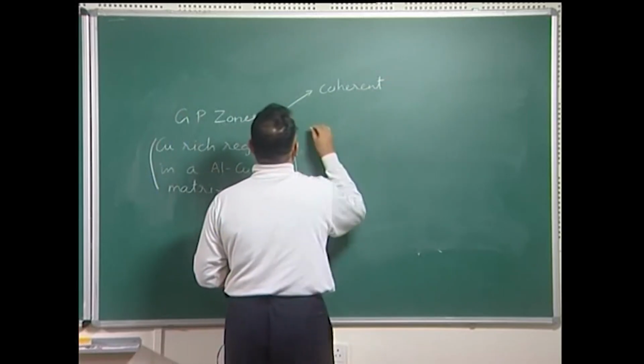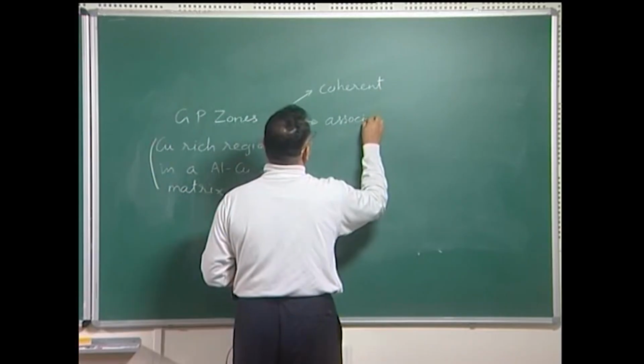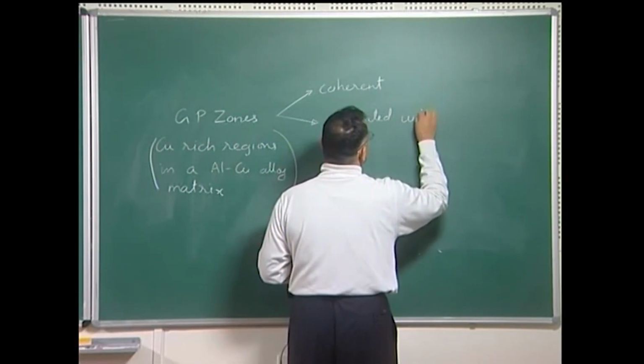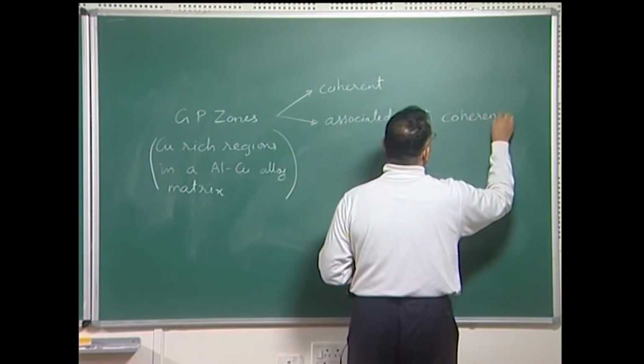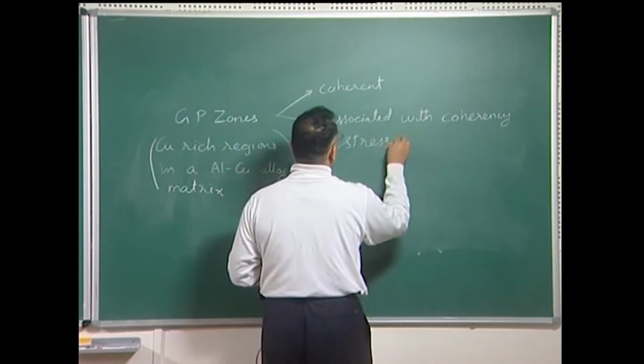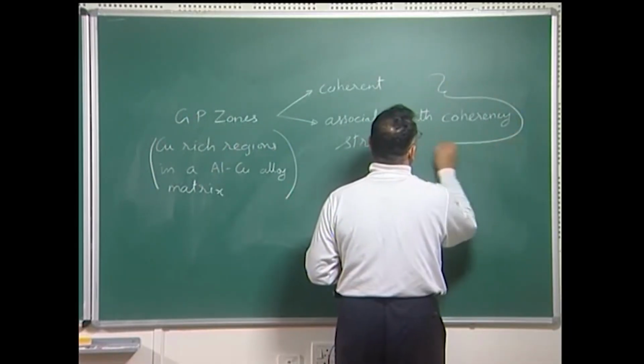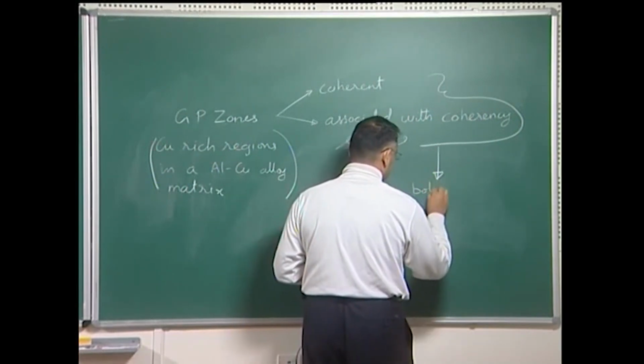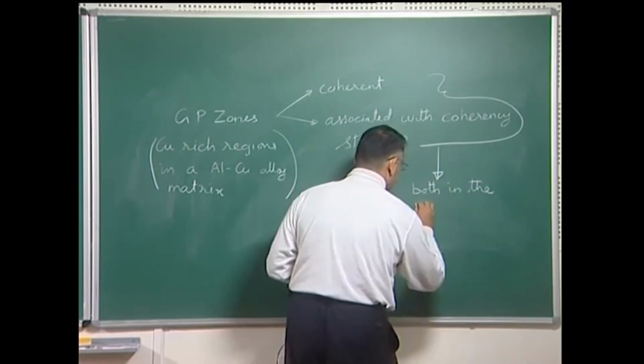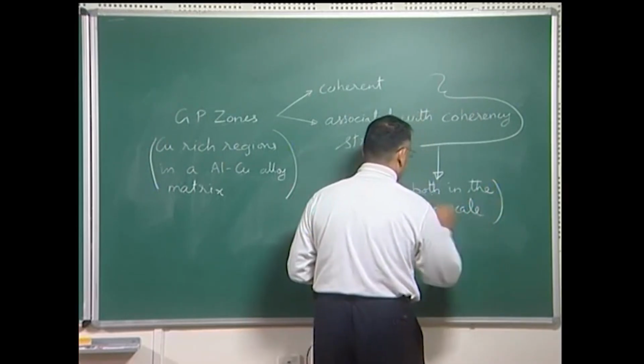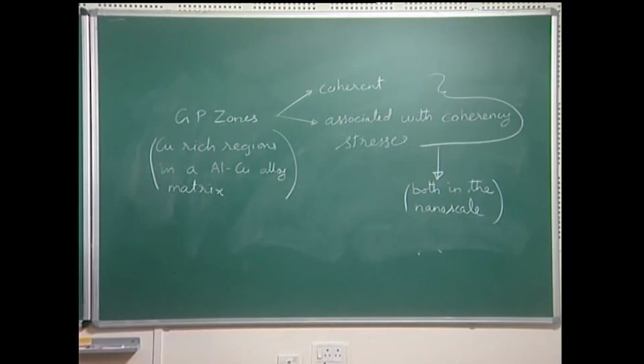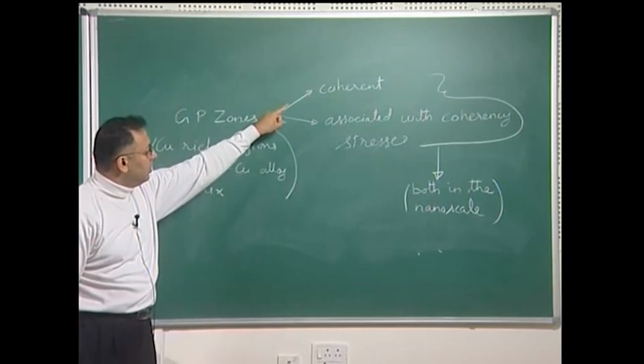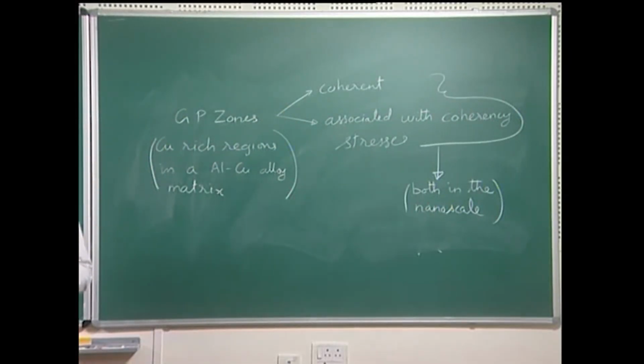And these GP zones are basically both the residual stress associated with the GP zone and the copper rich regions, the physical dimensions of that, both of these are in the nanoscale, and the presence of both of these is going to affect the properties of the material, the aluminum copper alloy, which has these GP zones.